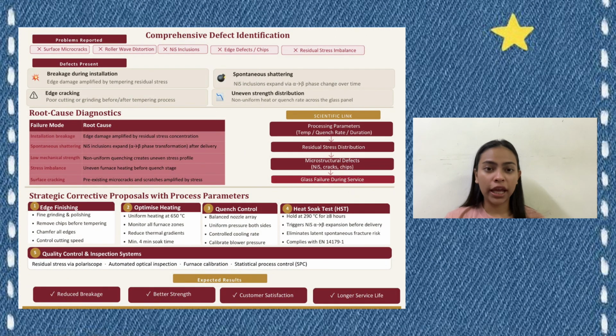But things can go wrong. If you look at the diagnostics panel, poor cutting or grinding before tempering causes edge cracking and surface microcracks. And if your furnace heats or quenches unevenly, you get a residual stress imbalance, leading to an uneven strength distribution across the panel. But the ultimate villain here is spontaneous shattering.